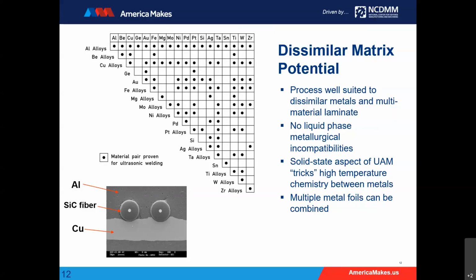On the left-hand side at the bottom, we have a micrograph that shows a unique combination. We have aluminum on the top, copper on the bottom, and silicon carbide fibers embedded into the matrix, so a true metal matrix composite. The one thing I would mention here is that the aluminum is bonded to the copper, but the silicon carbide is embedded in the aluminum. We're not actually bonding a metal to a non-metallic.